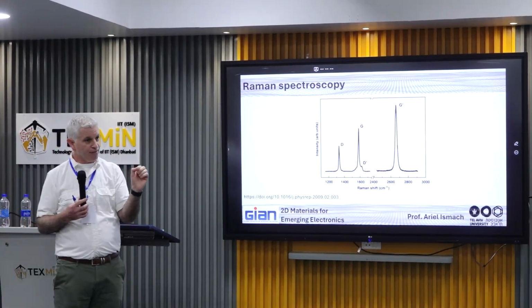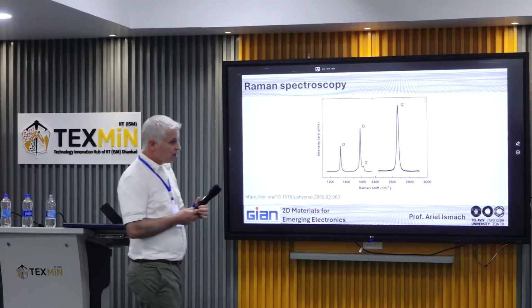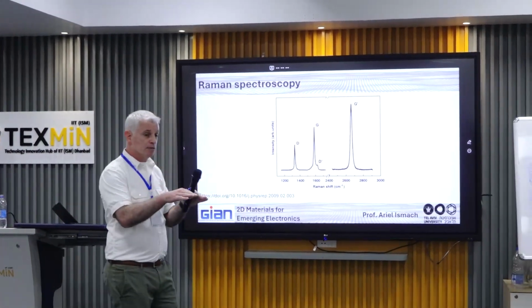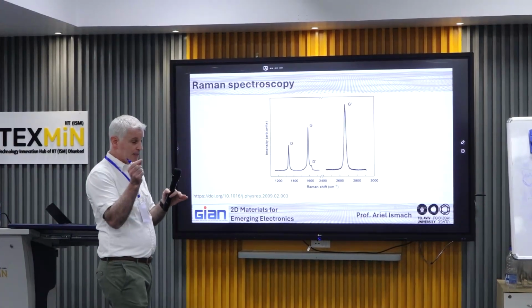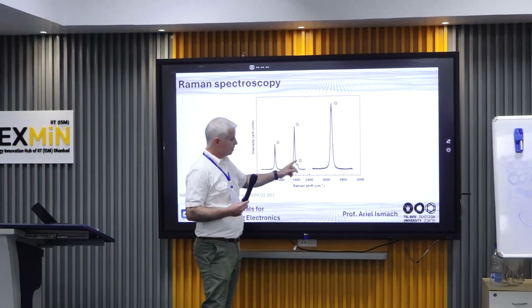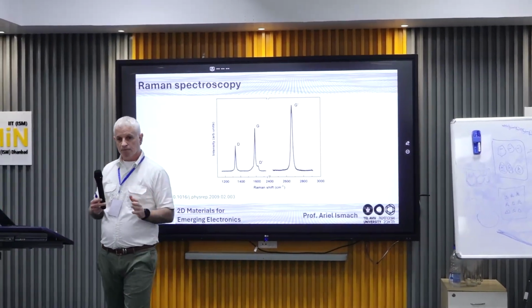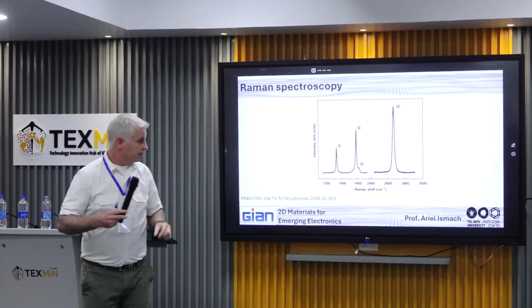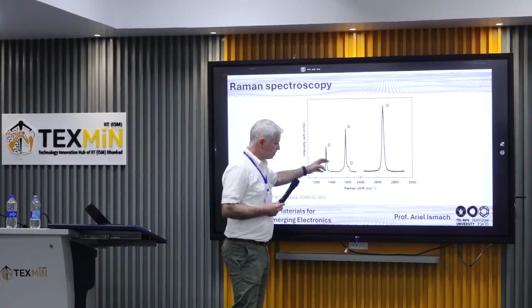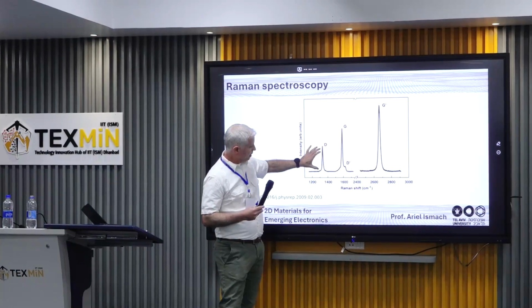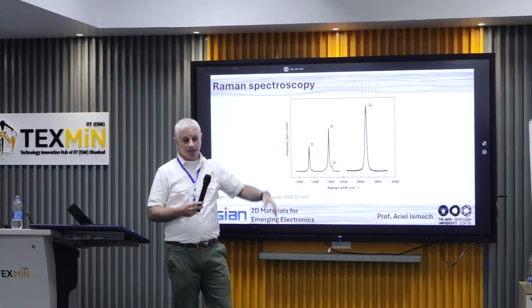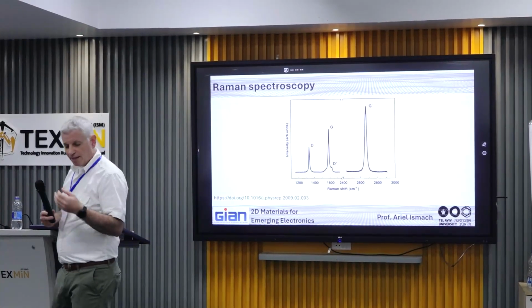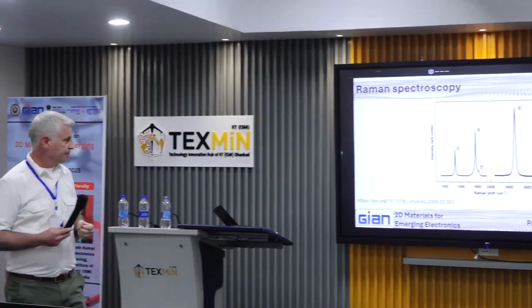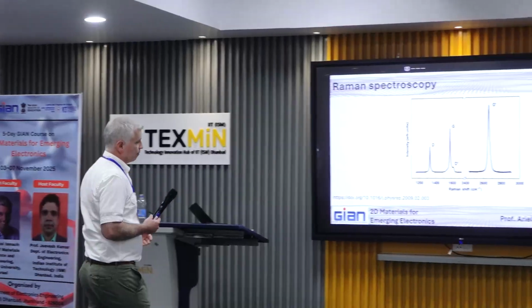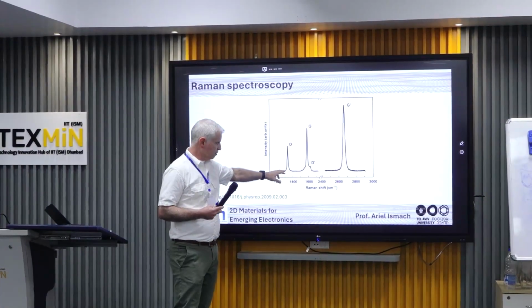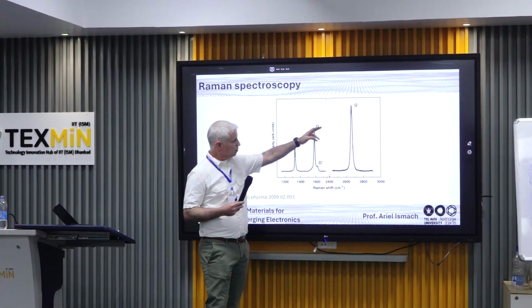Right? If you have slightly different events, for example, in the Raman modes, if you have some defects, the Raman modes, the vibrations will change slightly, and you will see that by broadening of the peaks. So in any spectroscopy, in general, the sharper the peak that you measure, usually by full width at half maximum, full width at half of the height of the peak, is a first indication of the quality of your material. And in this case, a good graphene, first of all, should have no D peak, so very small D peak, and a ratio of G to G prime very, very small.